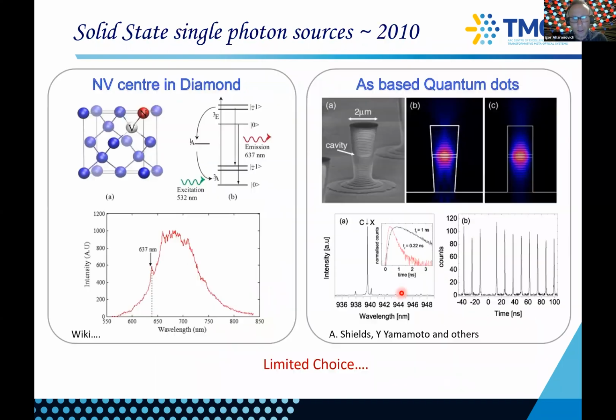So I guess it's interesting to go back in time to about 10 years ago. And in science, a decade can actually be quite a bit, but only 10 years ago, you really only had two systems. You had the NV center in diamond. It has a very broad emission. So for many applications like communications or interference, maybe not ideal because there are not many photons in this coherent zero phonon line. And you had the arsenide-based quantum dots, which you could already back then grow very nicely into pillar or Bragg stack cavities, and you can generate very good quantum dots, and plenty of groups doing this research.